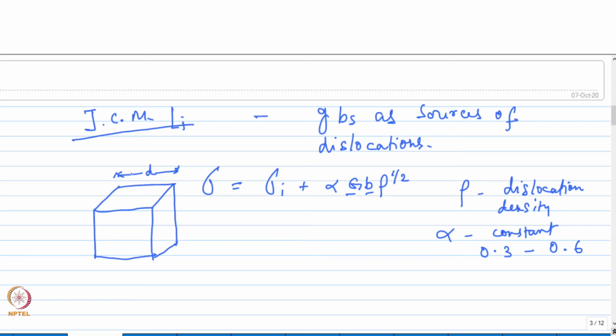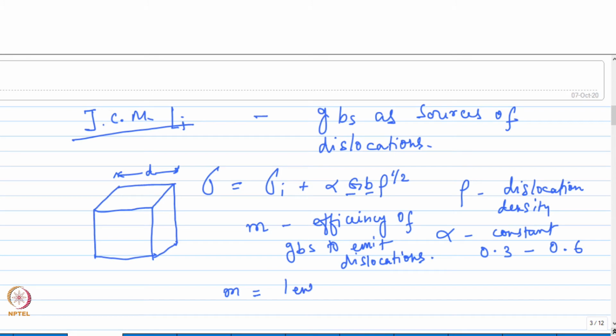So as I said before, the dislocations will be generated by the grain boundaries, and every boundary will have its own efficiency of emitting dislocations. So let's say M is the efficiency of grain boundaries to emit dislocations. And this is nothing but equal to the length of dislocation emitted per unit area of grain boundary at yielding.